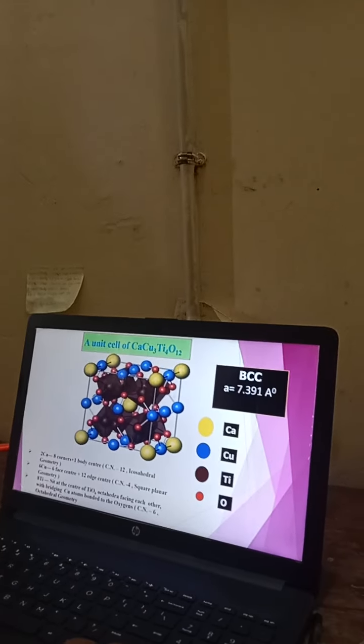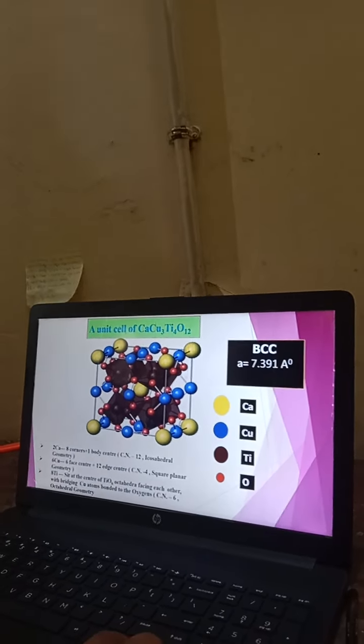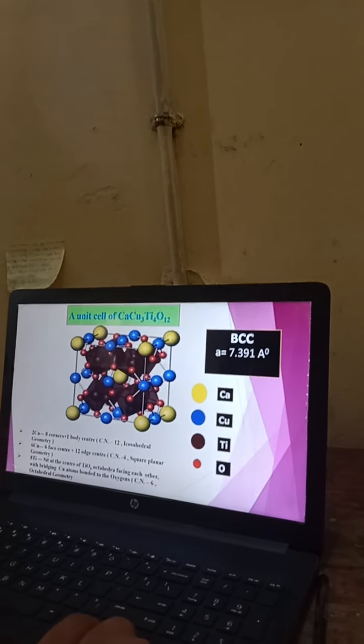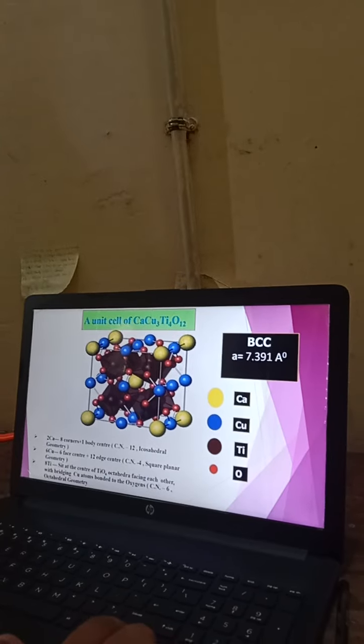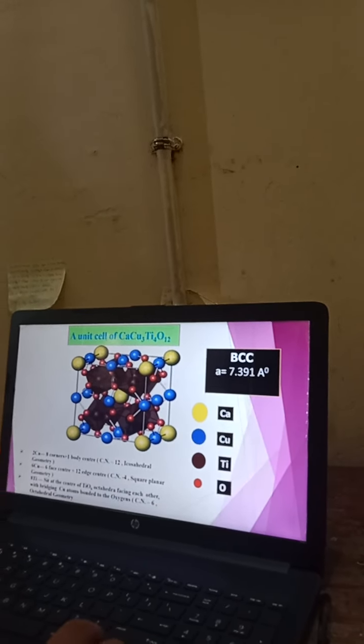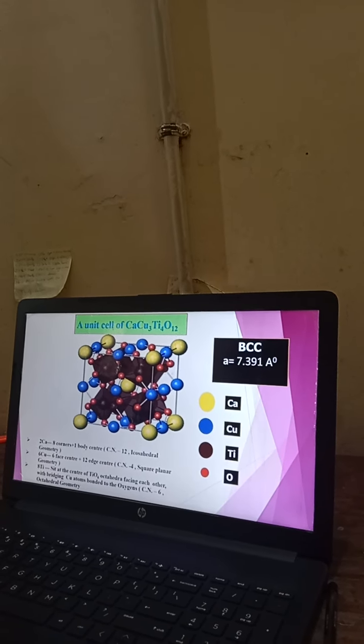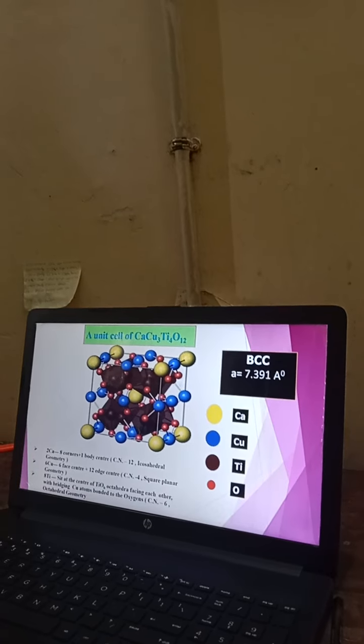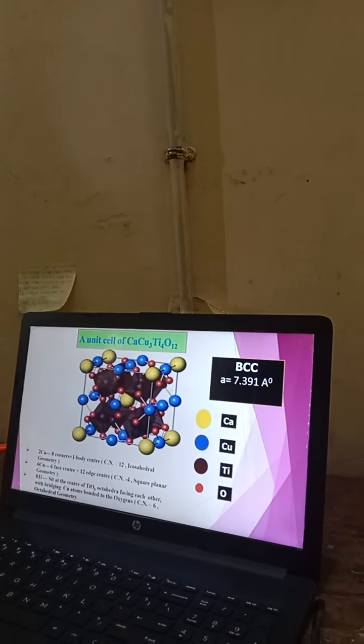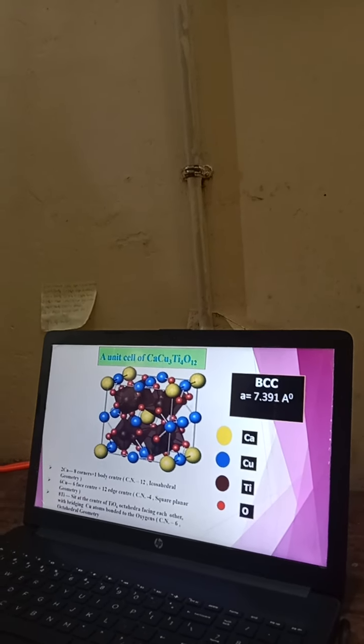The unit cell of CCTO. The calcium occupies the 8 corners of the cube and the body center, having coordination number 12 and icosahedral geometry. The 6 copper ions are situated at the six face centers and 12 edge centers, having coordination number 4 and square planar geometry. The 8 titanium ions sit at the center of the TiO6 octahedra facing each other, with bridging copper atoms bonded to oxygen, having coordination number 6 and octahedral geometry.